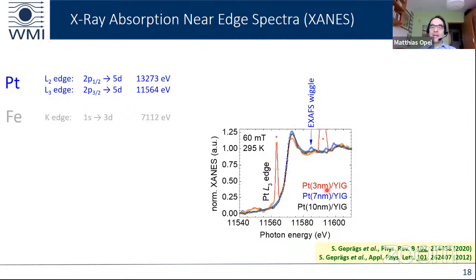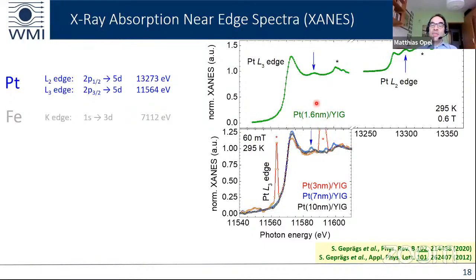So we have 2 more samples, one with a thinner layer of platinum, only 3 nanometers, and a thicker layer of platinum, 10 nanometers, on YIG. So all these 3 spectra follow the same line. Well, except for this peak, this is a diffraction, a Bragg diffraction peak, and also that one. I marked these diffraction peaks with asterisks, and they are not important here. So all the three samples show the same X-ray absorption line. We have an even thinner layer of platinum, only 1.6 nanometers, and even this layer shows the same X-ray absorption. This was all done at room temperature.